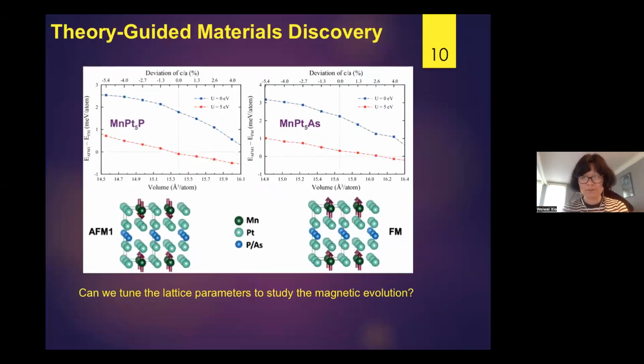So one thing we usually do is, for the 115 phase, the heavy fermion phase actually is very sensitive to the c/a ratio. So if you press it a little bit, it can make it go from superconductivity to magnetic, from magnetic to superconductivity. So one thing we did is we tried to simulate, okay, if we press the unit cell, what will happen? And we found out for the manganese system, if we press it, the magnetism will change from ferromagnetic to antiferromagnetic, but we cannot find the superconductivity.